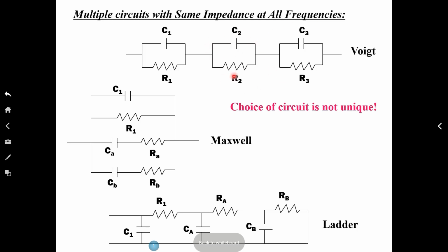And if you do see it, then indeed this one is the grain boundary element. Or you can change the electrode. You can make contact with platinum, or with gold, and see whether this component is changing.